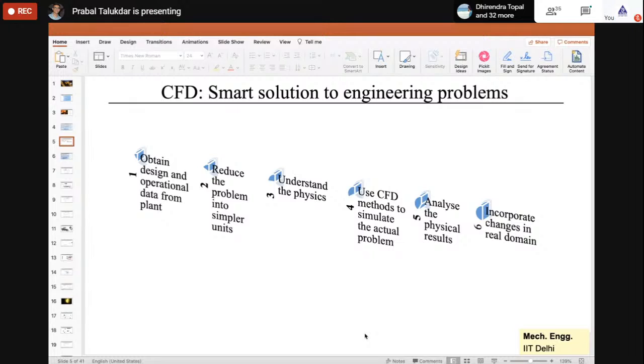So there are a few steps which have been written here. The first one is you obtain design and operational data from the plant, because whatever problem you are going to solve, you need to know what materials are used here and what operational conditions are used here, because you need to put those as input in the CFD simulations. You need to reduce your problem into simpler units, because in industry you have several things happening together, so you cannot solve everything together, right? For example, if you start from the tundish, then you do solidification in the mold, then you go to spray cooling. If you take everything together, it's a big problem. It's very difficult to solve the whole problem entirely. So you should try to decouple the problem into several small parts, so that you can get solutions in less time.